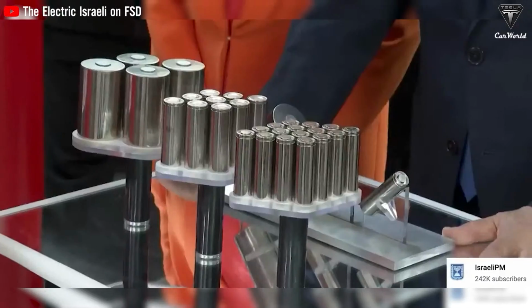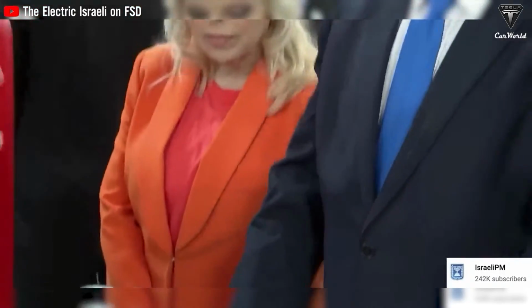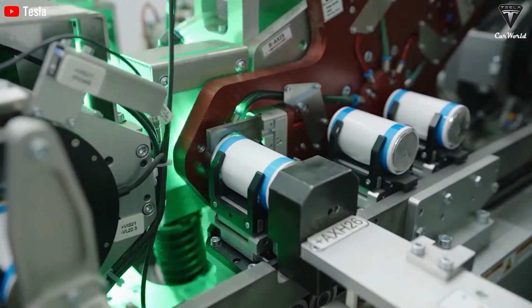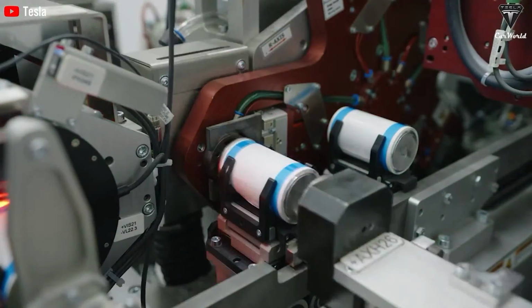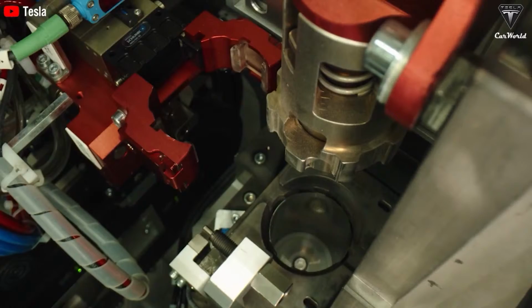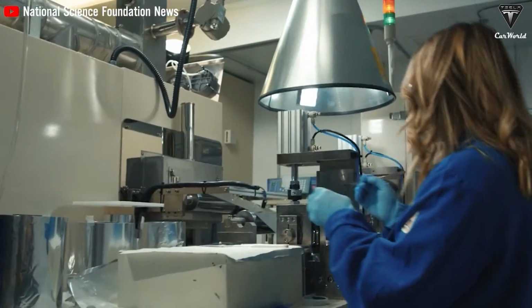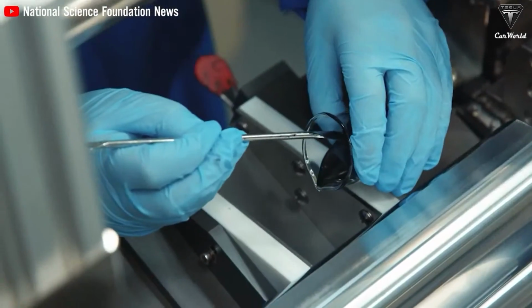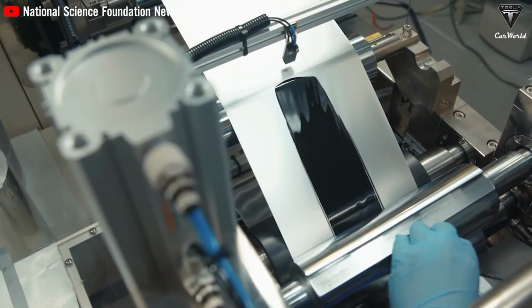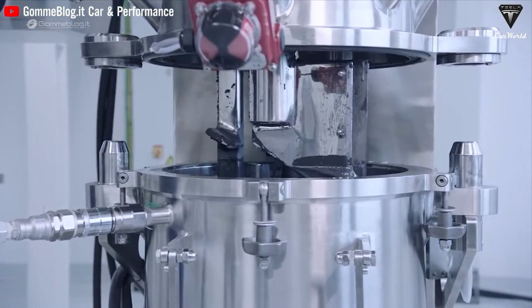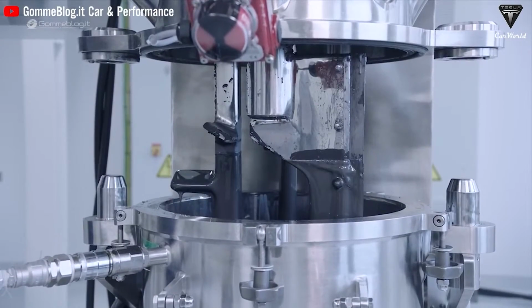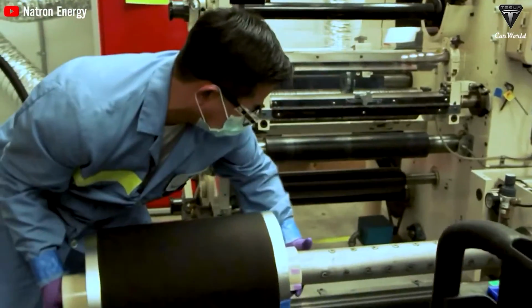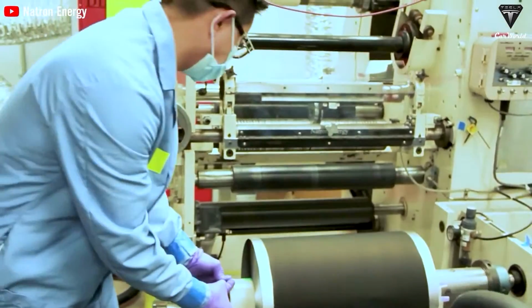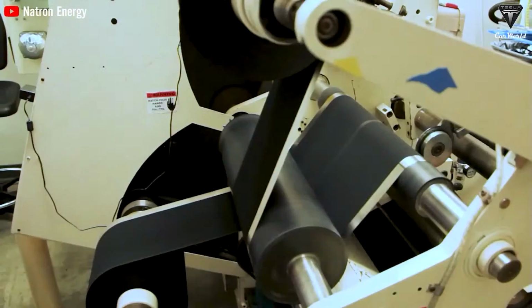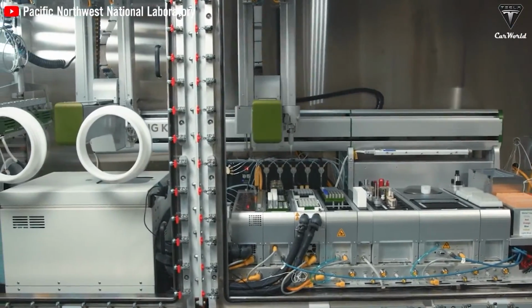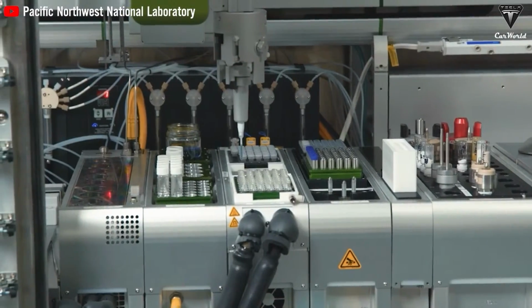A recent Tesla patent describes a method for multi-layer electrode films, where the main issue is the poor adhesion of the active material layer, like graphite, to the metal foil, leading to electrical loss and reduced storage capacity. Silicon, despite its high energy density, encounters issues with volumetric expansion during battery cycles, and that makes it challenging to get long-term performance. This patent proposes a multi-layer approach, with a silicon-rich layer in the middle and higher adhesion layers on the top and bottom to maintain the stability of the active electrode structure, and that improves connectivity and minimizes separation inside the battery.